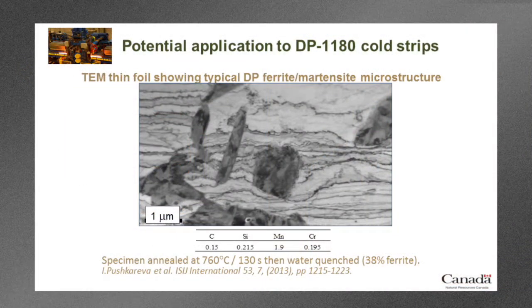Here's an example of the microstructure of a dual-phase steel. This is a TEM image. So it's a thin foil this time, it's not an extraction replica. And you can see the two phases here. The phase with the wavy lines in it, this light phase here, this is ferrite. And these wavy lines are actually bend contours. It's an artifact that you can see inside the TEM. And this darker phase here, where you can see there's a lot of contrast in there, that contrast is actually due to dislocations. This is a hard martensitic phase. This is the reinforcing phase. And the thing to note is that these martensite islands are very small. They're only a few, maybe a micron, sometimes much less than a micron in size.